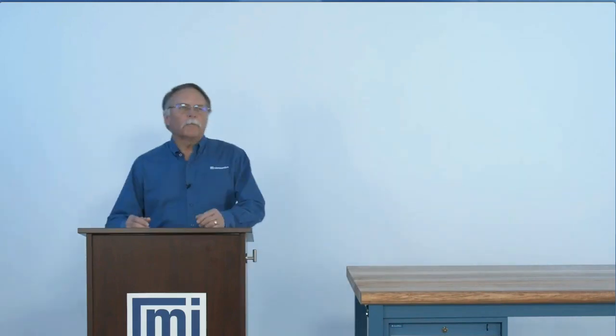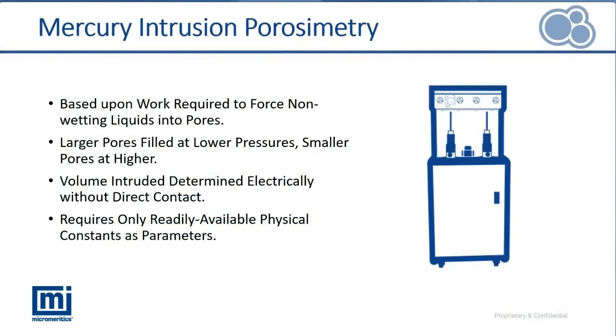Okay, let's take a quick look at how the AutoPore operates, the technique behind Mercury Intrusion Porosimetry, and then we're going to take a quick look at some of the software features as well. So, Mercury Intrusion Porosimetry, we determine pore size distribution based upon the work required to force a non-wetting liquid into open capillary pores. Now, the larger the pore, the easier it is to get the mercury to expand into that, because we are creating surface area of the mercury, so we're fighting against the mercury surface tension. So the larger pores are going to fill at lower pressures, smaller pores filling at higher pressures. We can determine the pressures at which they're being filled with the use of a pressure transducer.